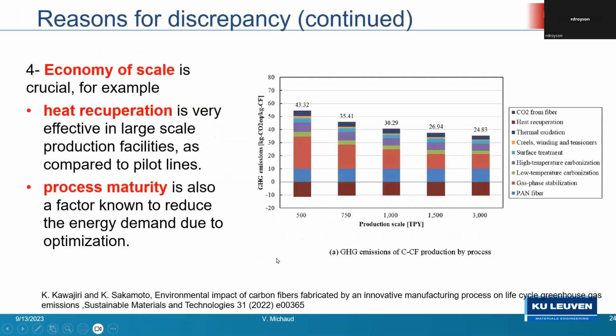And finally, there is a big impact of economy of scale, depending on the amount of carbon fibers you produce. And this is a recent publication by some Japanese researchers. If you go from 500 ton per year to 3,000 ton per year in a certain production plant, then you see that the CO2 emission is going down from 43 to about 24 kilograms CO2 per kilogram carbon fiber, and you end up with a value which is very close to the value in this JCMA data. And the reason for that, of this economy of scale, is of course the potential for heat recuperation in large scale production and the level of process maturity. The more you produce, the better you understand the production, the more efficient you can make the production. So this is a fourth reason why there could be this big difference between the high LCA data and the low JCMA data.